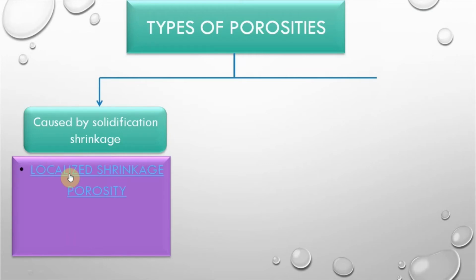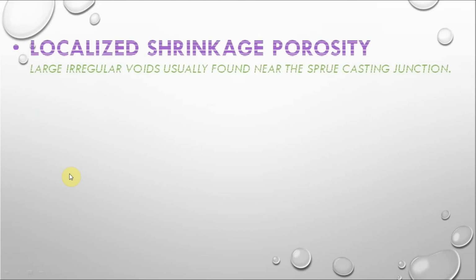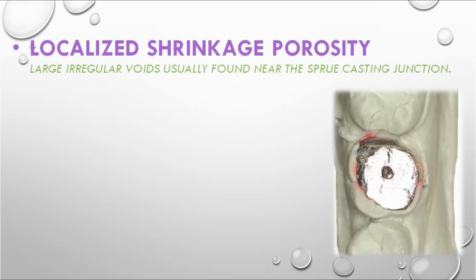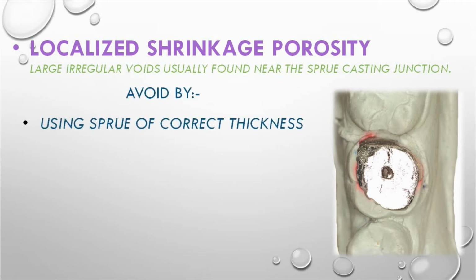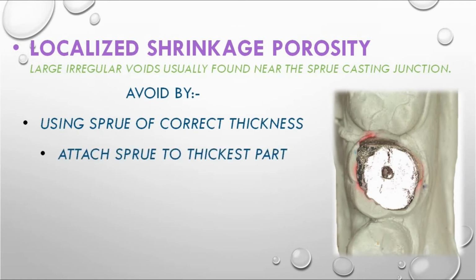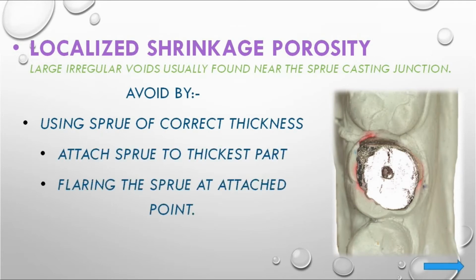localized shrinkage porosity. Why this happen? Usually sprue former लास्ट में solidify होता है, it act as reservoir, लेकिन इसमें रिवर्स होता है जिस कारण कास्टिंग की solidification shrinkage compensate नहीं हो पाती. Large voids are formed near sprue casting junction, avoided by using sprue of correct thickness and attach it to the thickest part of wax pattern. Moreover, flare the sprue at attachment with pattern.